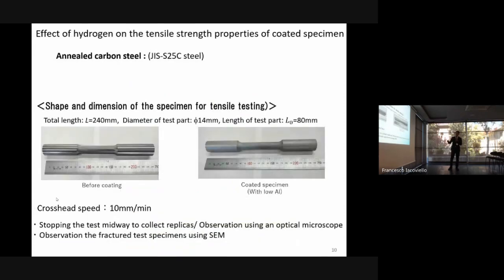Now, I also conducted a tensile test of coated specimens. The material is carbon steel S25C, the shape and dimension are like this, and the crosshead speed is 10 millimeter per minute. During the tensile test, I stopped the test and took a replica at the lateral surface in order to observe the crack initiation at the lateral surface. And I observed the fracture surface using SEM.